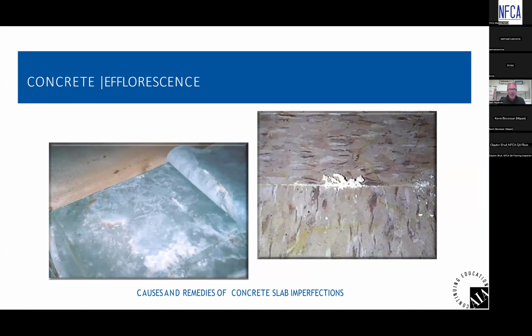Efflorescence is a process where excessive moisture takes the natural salts and drives them to the surface. Pretty extreme situations, as you see here. The right picture is salt formation through VCT, excessive moisture driving the natural salts of the concrete, and you've got white salt formation at the surface.